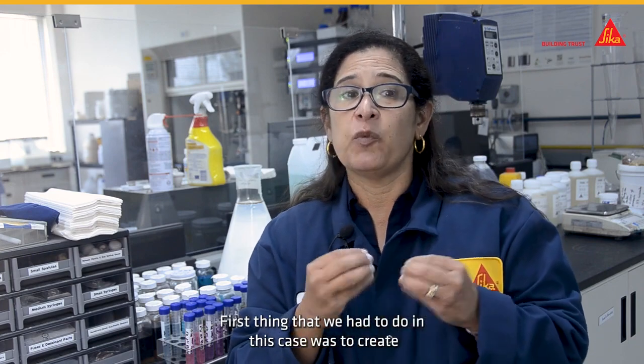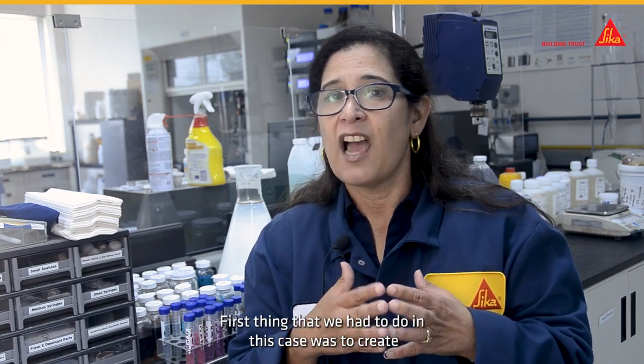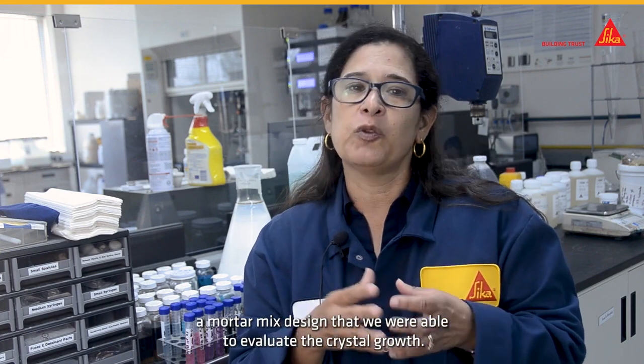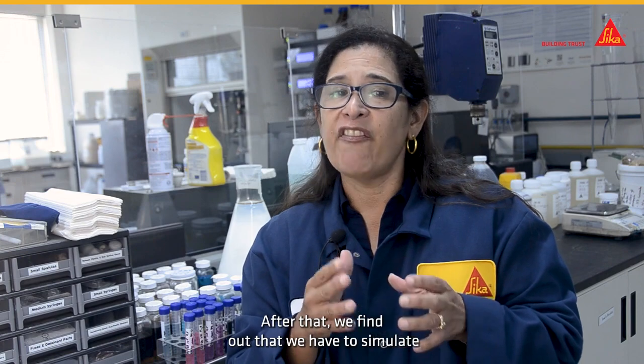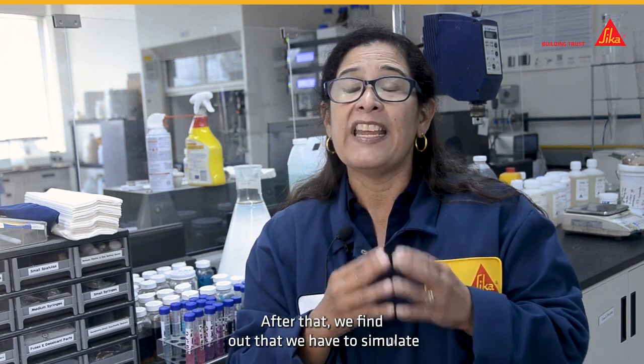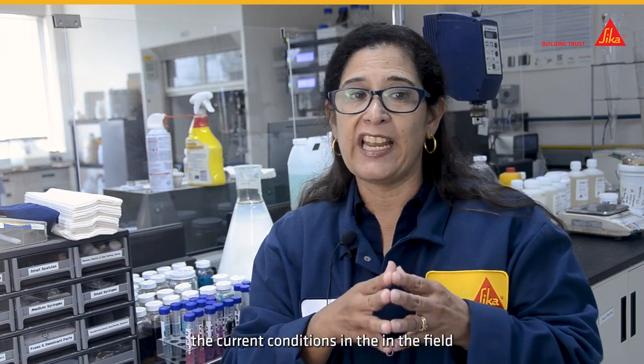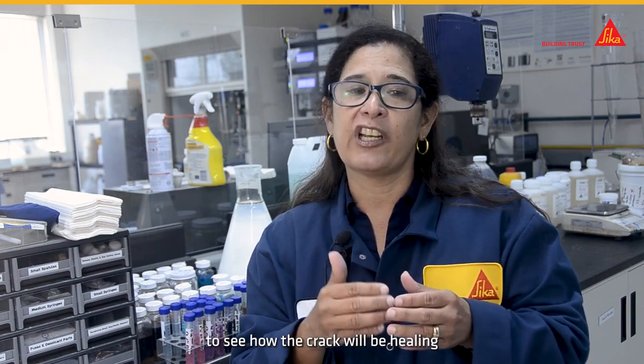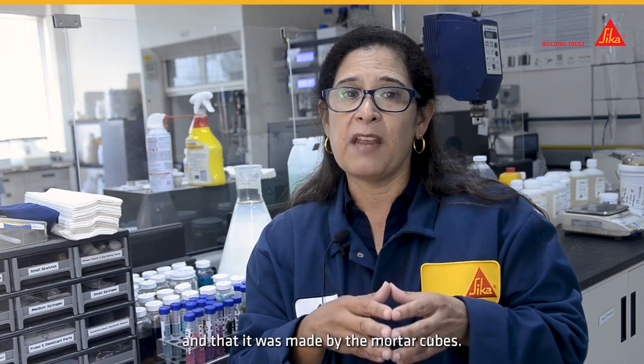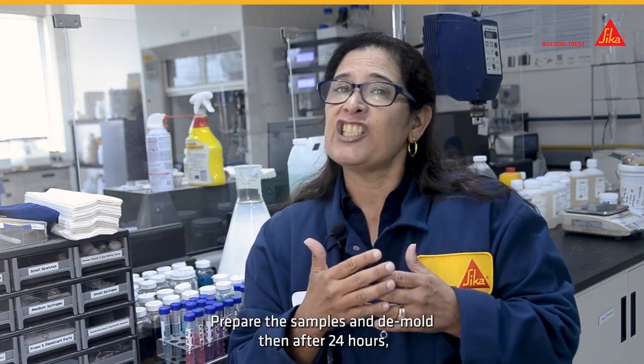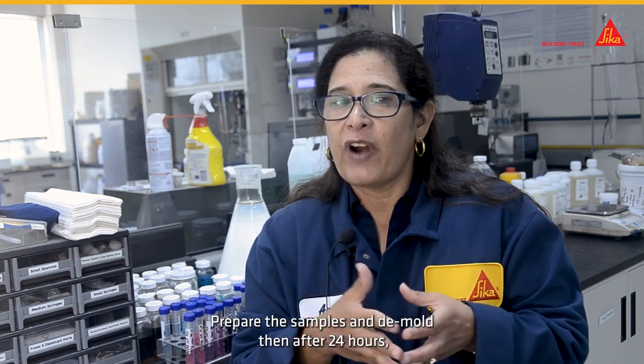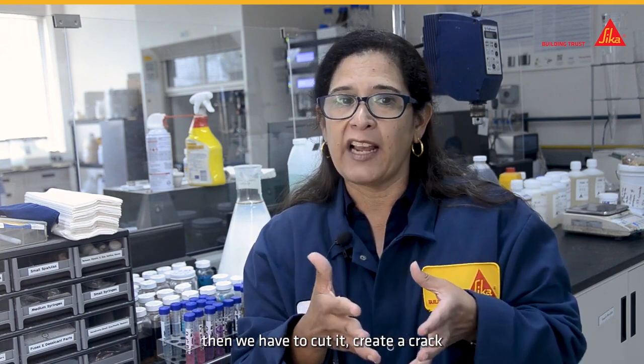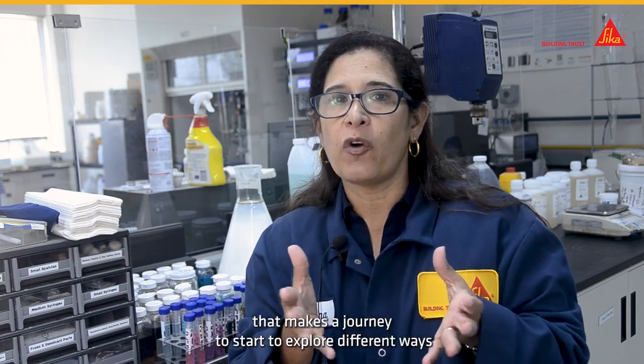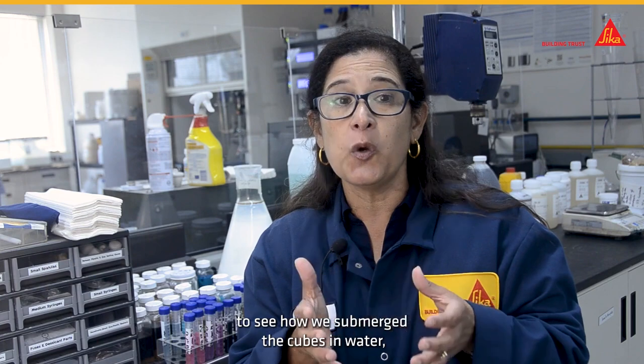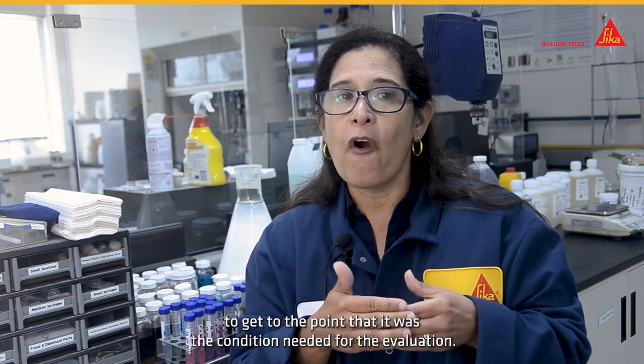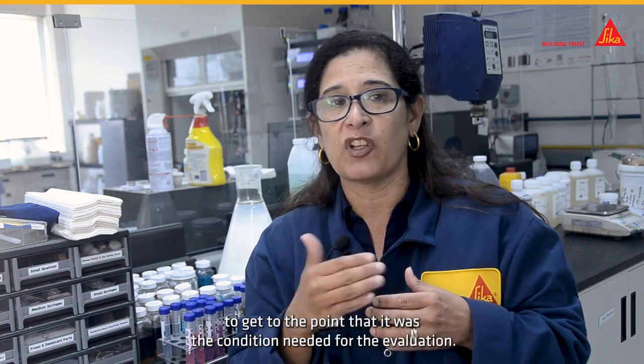The first thing we had to do was create a mortar mix design that would let us evaluate the crystal growth. After that, we found out that we had to simulate the current conditions in the field to see how the crack would heal, and that was done with mortar cubes. We prepared the samples and demolded them after 24 hours. Then we had to cut them and create a crack. That started a journey to explore different ways of submerging the cubes in water to get to the condition needed for the evaluation.